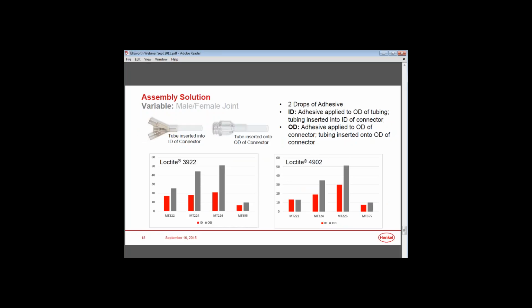And then lastly, we wanted to take a look at what if we had an assembly in which the tube was inserted onto the OD of the connector. In most cases, the most challenging bond is what we've done up until this point on all the data, which is the tube inserted into the ID of the connector. So we wanted to see would you gain or improve your strength with a different joint design. And you could see in this case that we did see improved bond strength for assemblies to the OD of the connector. So highlighting here that you do have options for increasing your bond strength, such as things like joint design. And of course, with adhesives, there's always many different alterations and variations that you can make in order to increase your bond strength.